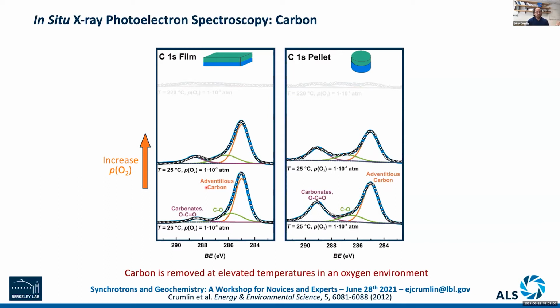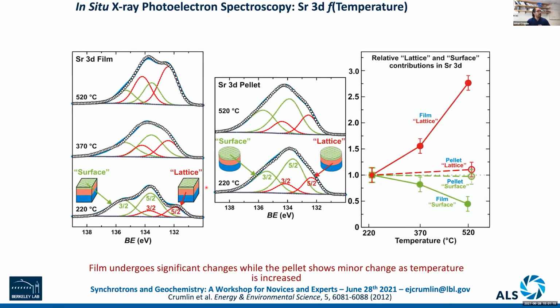And we don't see any change because we're at room temperature, but now we can even start to heat. And when we heat, we can see that the carbon even burns off. It just decomposes and goes away. So carbon is even in this particular case removed from the analysis. We don't even have to worry about it. Then we look at the other aspects with regards to the other elements within the sample.